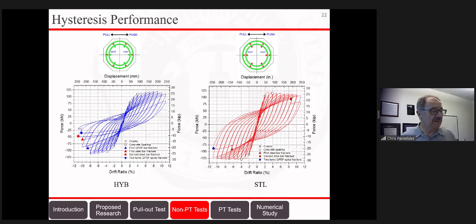So what you can see in this picture is that on the left, on the hybrid column, we have an increased lateral force that increased gradually up to about 9% drift ratio, which is a very large drift ratio. And on the right, in red, you can see that the steel column performed well, maybe even better, which has a very high stiffness in the beginning. You can see the slope here, up to 3% drift ratio. And at that point, as is typical for these steel columns, it achieved a very good plateau.